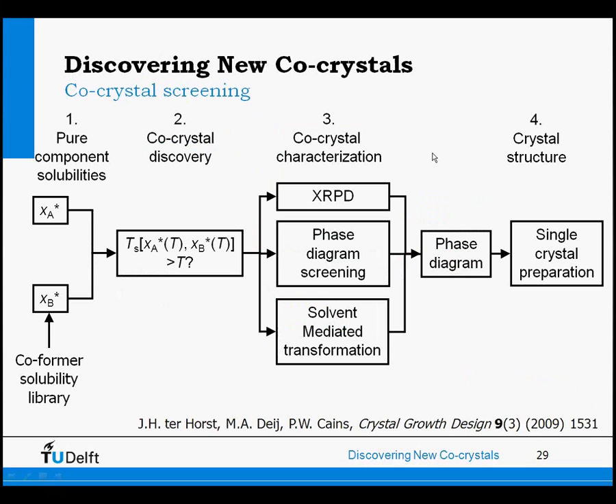So then we come to this screening method. So I talked about the first two steps, so determining the pure component solubilities, and those solubilities determine where you have to screen for a co-crystal. So we choose a certain temperature, determine the pure component solubilities, make a sample with composition of these pure component solubilities, and then we measure the saturation temperature. And if that saturation temperature is higher than our reference temperature, then that is a good indication that we have co-crystals.